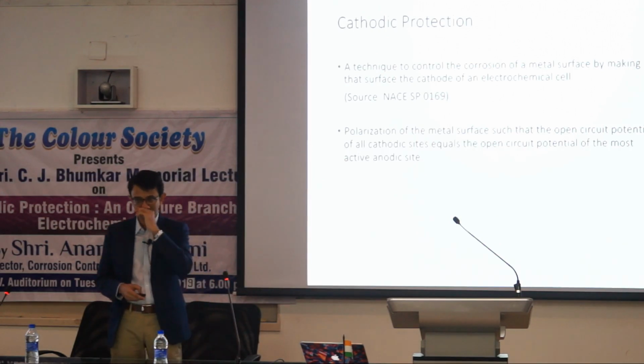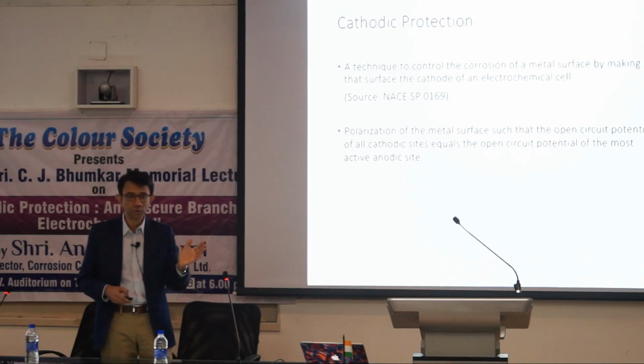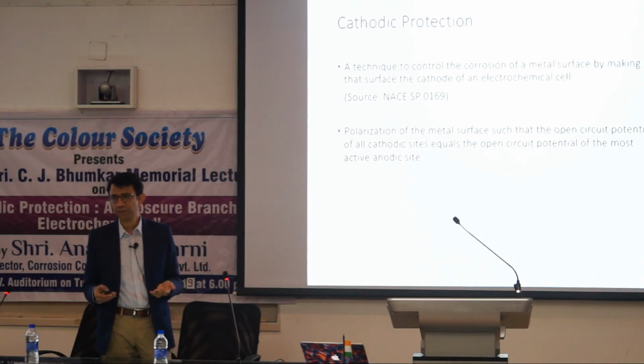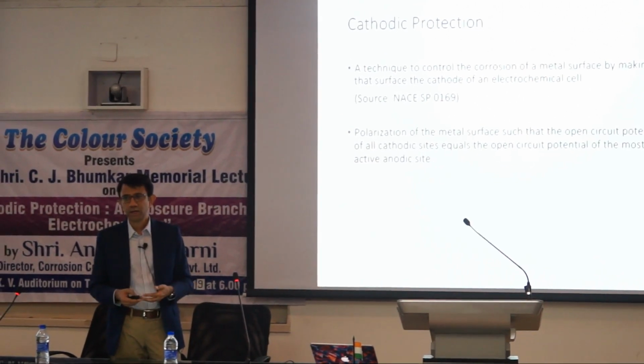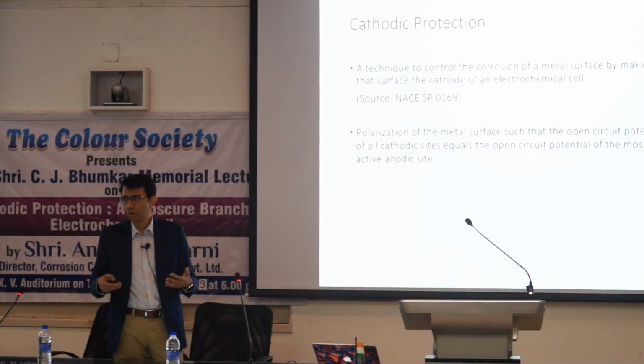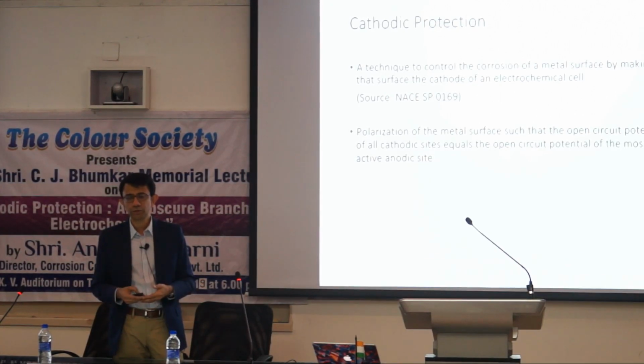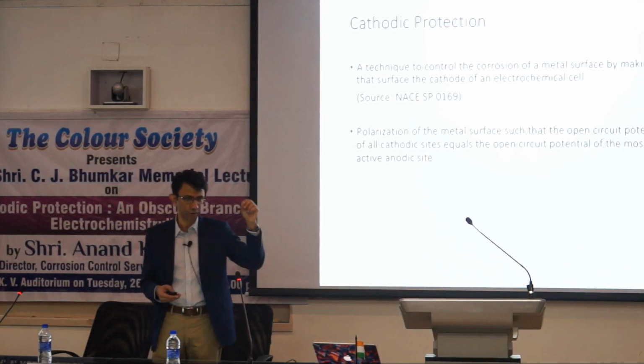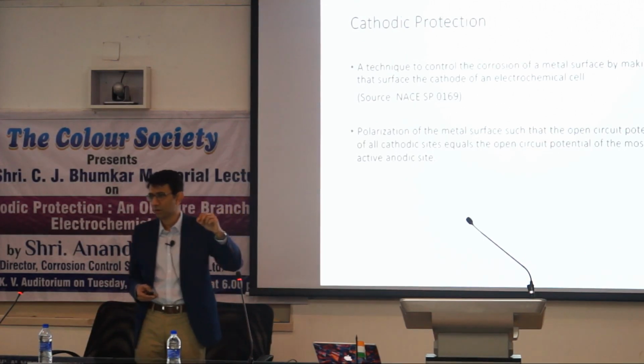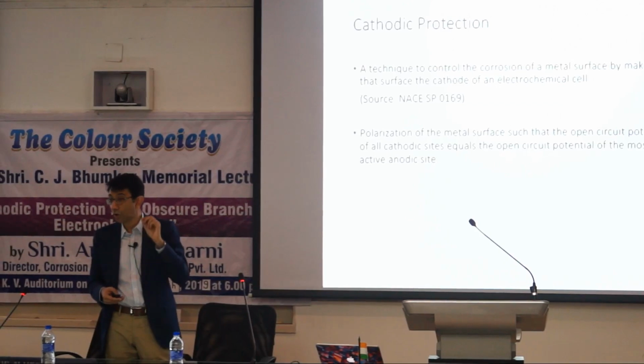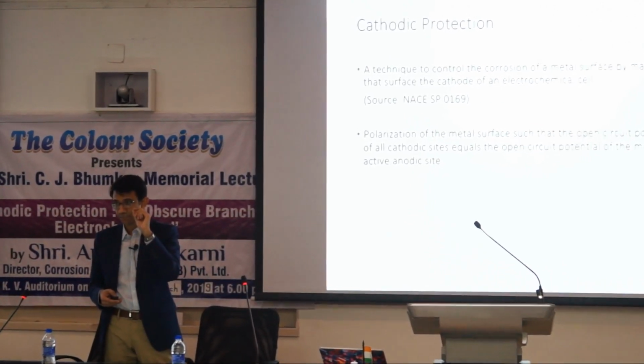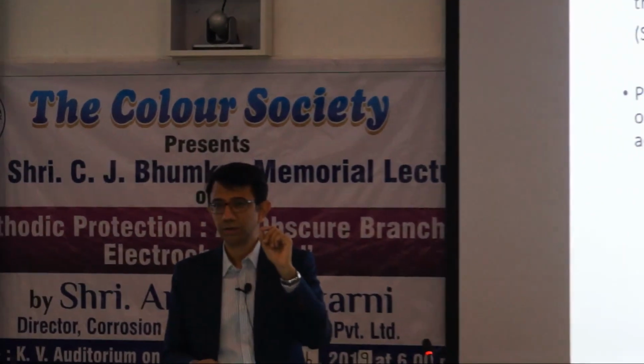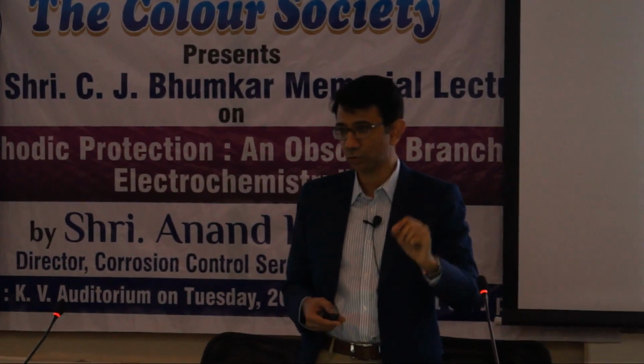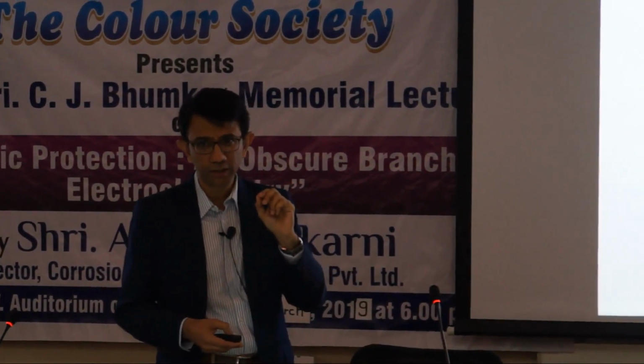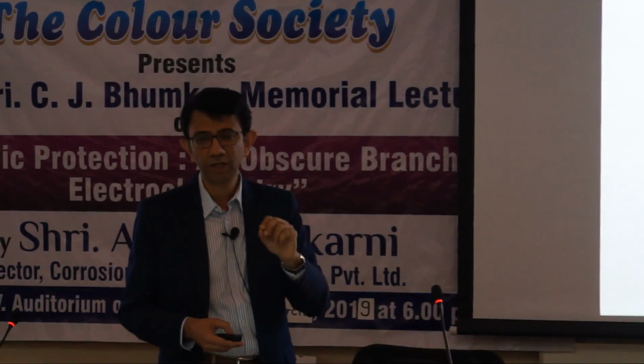Mr. Raghuraman was talking earlier about the fact whether you want CP or whether you want coatings. Really, they are both complementary. You need coating, obviously, and you need CP because you don't need a lot of CP, but you need a little CP to ensure that those small, tiny defects in the coating, whether it is 1 square millimeter or 1/10 of a square millimeter or 1/100th of a square millimeter, the smaller the defect in the coating, the greater the risk, exponentially greater the risk of corrosion. So we don't need much CP today, but if you didn't have CP, we are definitely going to have failures.